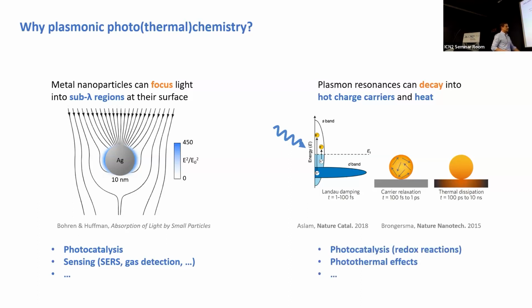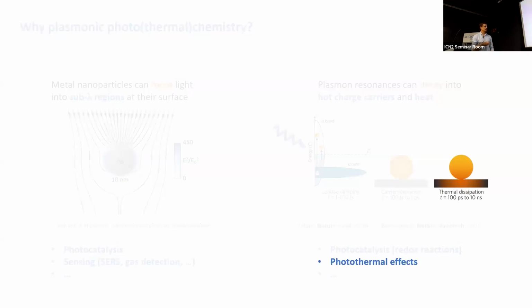And of course, we can think of ways in which we can apply this phenomenon for catalysis and for chemistry. If you are fast enough, you can harvest these electrons and holes and do, for example, reduction reactions and oxidation reactions. And we have done quite a lot of work on, for example, synthesis of nanomaterials driven by hot charge carriers. But if you're not fast enough, you're still heating up the nanoparticle, and any chemical reaction goes exponentially faster at higher temperatures. And so you can heat up locally and activate chemistry locally. And that's actually what I want to show you a couple of results on, really about this photothermal effect. So translating photon energy into heat and controlling that heat both at the nanoscale and on ultrafast timescales.